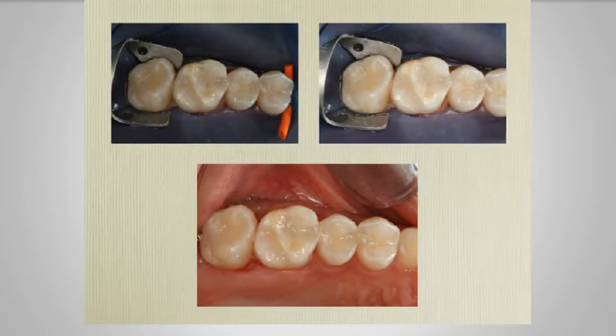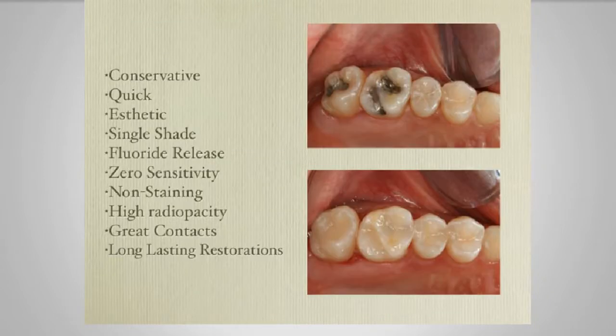So I'll show you a little before and after. So what did we do here? Basically, we did a pretty conservative restoration. We did it pretty quickly, and you're placing the adhesive in less than a minute. Your composite is curing 2 millimeters at a time and at 10 seconds each. So it's aesthetic. This is a single shade that we're using. Basically, all of these that I wind up doing here are single shade materials that have a great chameleon effect that blend very, very well.